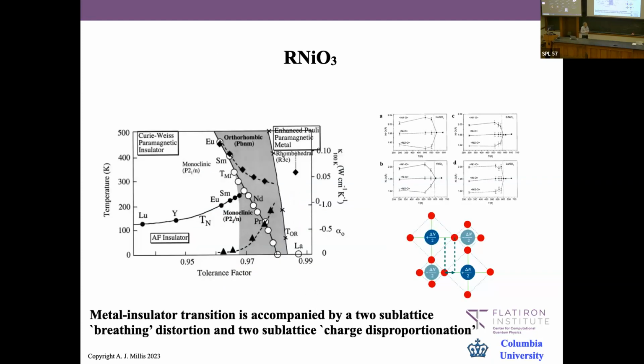Yet another example, the Republican in name only compound. R stands for one of the different rare earth or actinide series. This material, depending on what material you put, has a metal insulator transition at some temperature. For a wide range of parameters, the metal insulator transition is at a much higher temperature than the magnetic transition. The metal insulator transition is first order. It's associated with a large change in resistance, and it's associated with a change in the mean nickel-oxygen bond length.